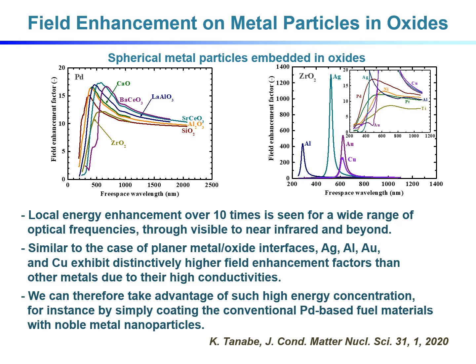Similar to the case of planar metal oxide interfaces, silver, aluminum, gold, and copper exhibit distinctively higher field enhancement factors than other metals due to their high conductivities. We can therefore take advantage of such high energy concentration, for instance by simply coating the conventional palladium-based fuel materials with noble metal nanoparticles.